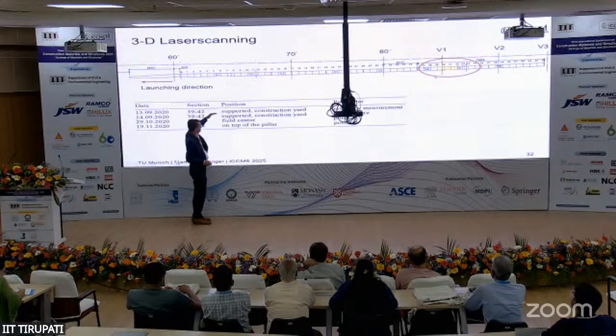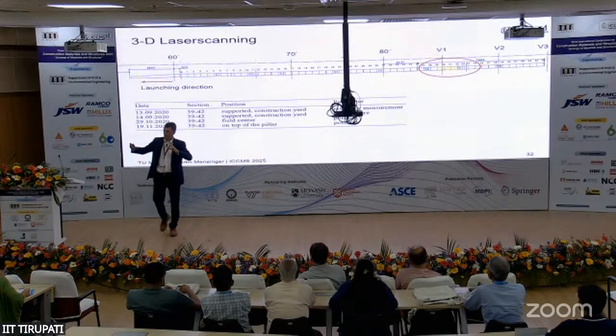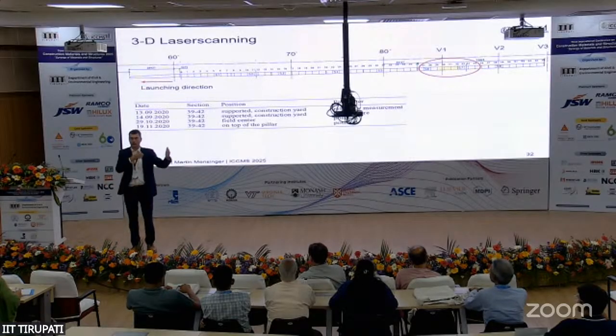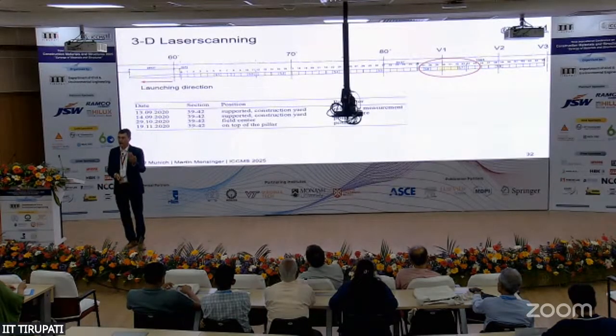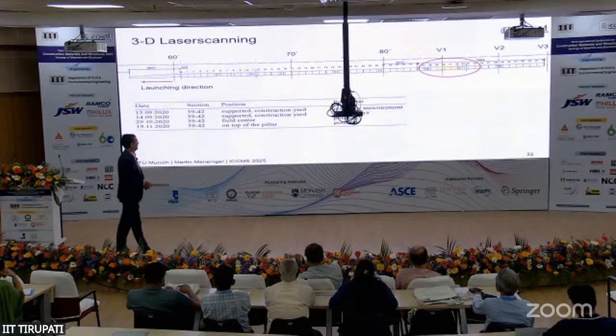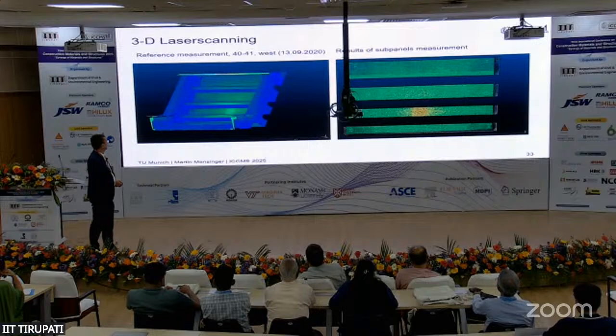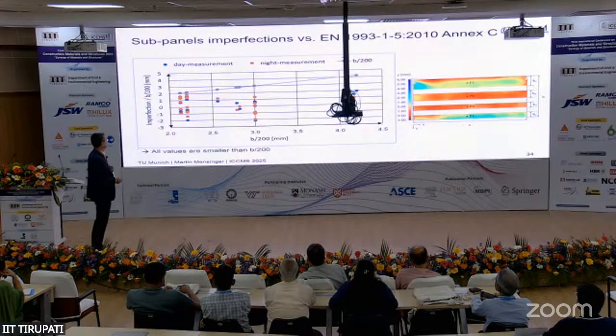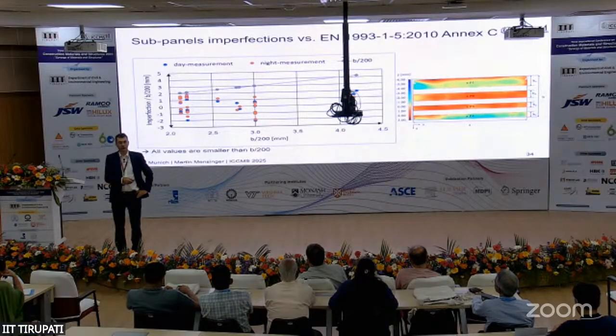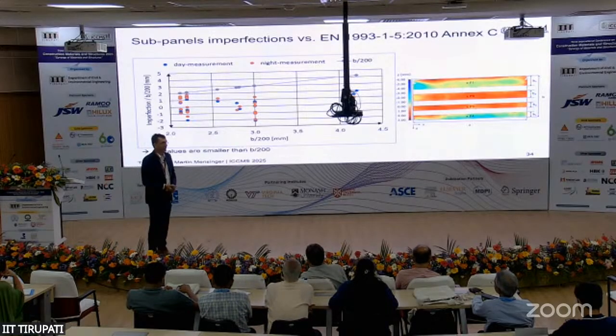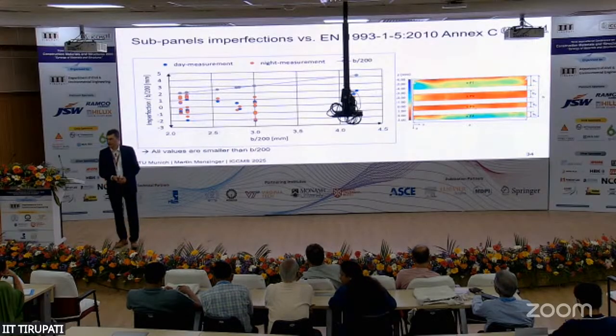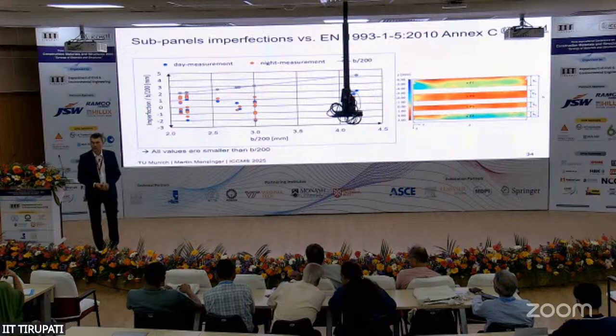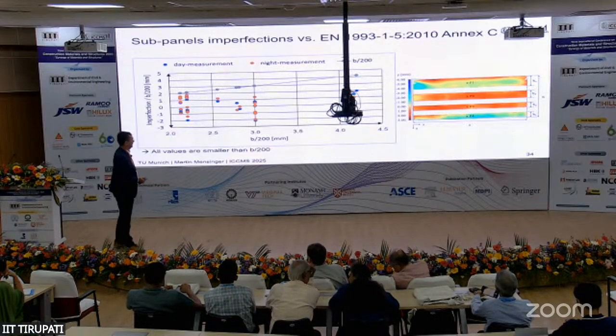We measured at daytime, in the night, and then during launching, when those webs were located more or less at midspan, and in another case where they were located above a pillar, where we also had these cross-directional stresses from the bearings. And here you see just a small figure of that. The interesting result is on this slide. You can see the assumption of Eurocode 3 part 1.5, the gray line, is safe-sided. So there's good news. And we also found out that they lead to pretty realistic results compared to our tests later. Therefore, the imperfections defined in Eurocode 3 part 1.5 can really be used for finite element calculation of the load-bearing capacity of those panels.